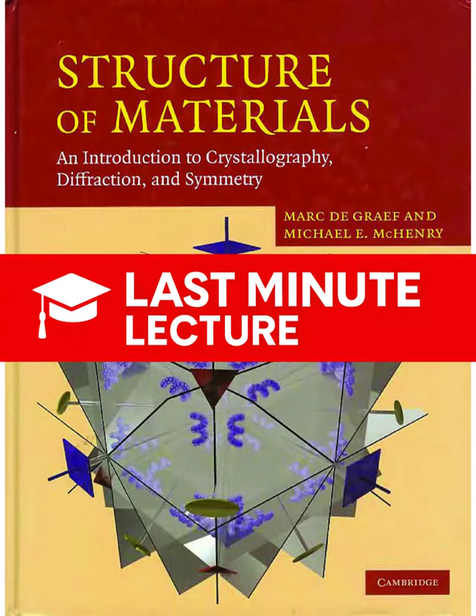Okay, solid circles for the top half and for the southern hemisphere. We just use the opposite pole. Points in the southern hemisphere are projected from the South Pole, S, up onto the equatorial plane. So that ensures they still project close to the center, keeping the map readable. Exactly. And to tell them apart, these points are represented by open circles. This distinction between solid and open circles is absolutely fundamental. It tells you immediately which way the plane is facing in 3D space.